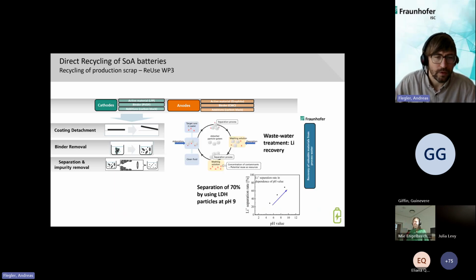And we also use a lot of aqueous-based processes. We see that we have a lot of lithium in the process water, and here we also have some activities to recover lithium out of the process water. Here we develop some adsorber particles. We put them in the